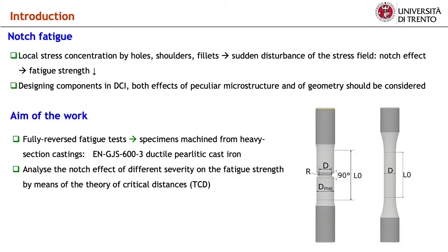For this purpose, in this work, we will explore the fatigue strength of ductile cast iron by performing fully reversed axial fatigue tests on plain and notched specimens carrying notches of different severity, and we will try to interpret the experimental results according to a critical distance approach.